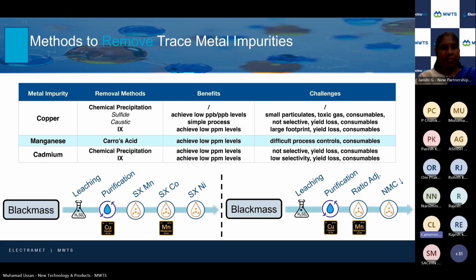And given that the old battery chemistry tends to be 622, 532, et cetera, that's not conducive to making what we want, which is 811. This high nickel content battery gives the high energy density, high power density materials. So they need to modify the ratios in this mixture to satisfy the conditions to make 811. And in order to do that, they usually have to remove manganese and cobalt. Well, removing the manganese is very tough in these solutions. Removing cobalt can be done in different ways, but you have to do this adjustment. And so we'll get into those specifics a little bit later on.